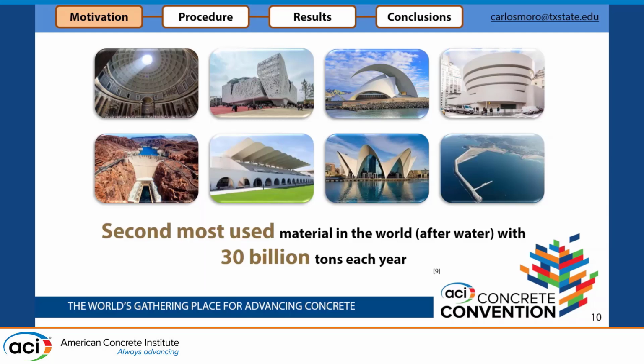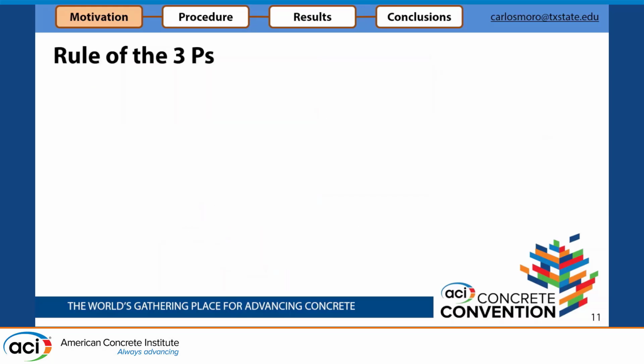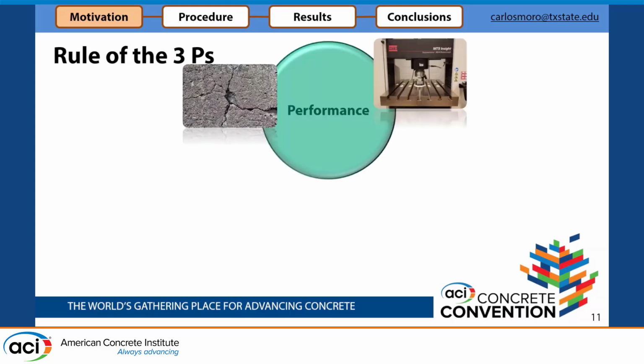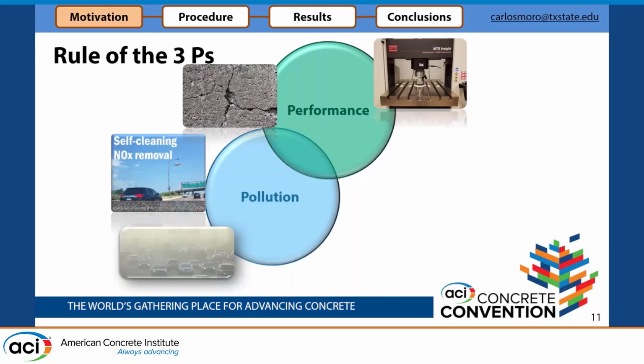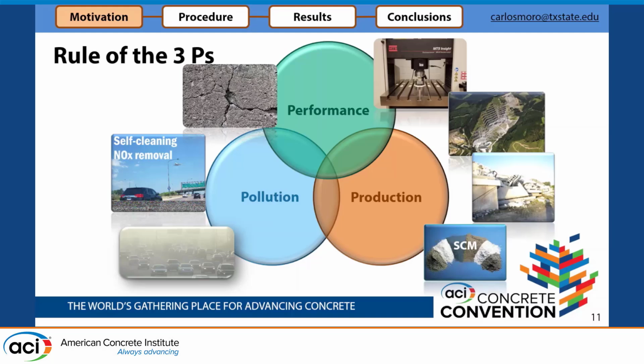Since it's so highly consumed, a small impact will lead to a huge benefit in the environment. So I like calling it that sustainability in concrete materials is based on the rule of the 3 Ps. The first one is performance. If we increase the performance of our concrete, we can reduce the cement content needed to achieve that performance, so we will reduce the emissions. We also can reduce pollution directly with different beneficial effects during the service life, like promoting CO2 uptake or a photocatalytic effect.